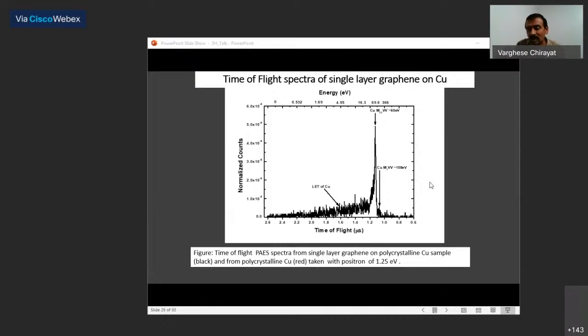Now, what should the graphene look like? Graphene should have a nice carbon and oxygen peak and a small tail like this, right? But lo and behold, there is a lot of intensity up there in the low energies. What is that? We were confused because we were at energies of 1.25 eV. There is no way that we will get electrons other than due to the annihilation process, the annihilation induced Auger process. Now, what Auger process can give you these low energy electrons?